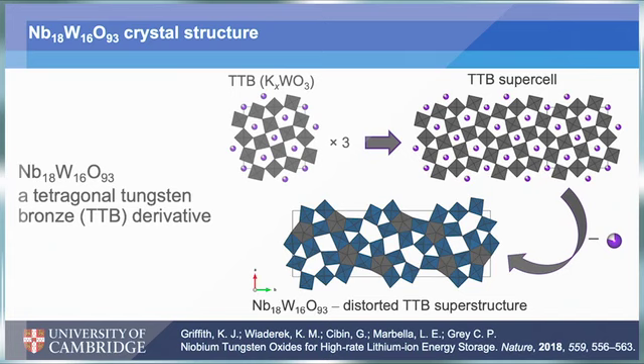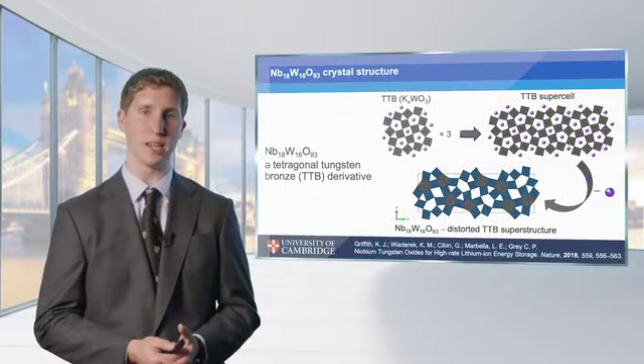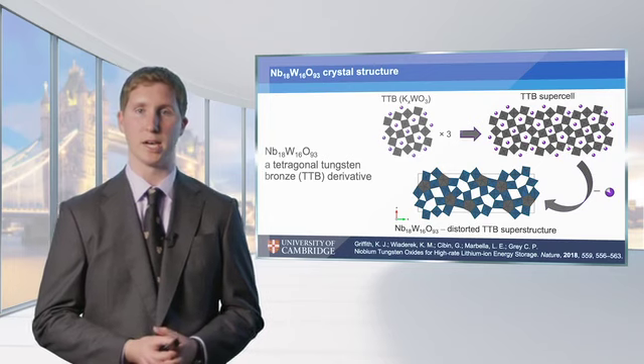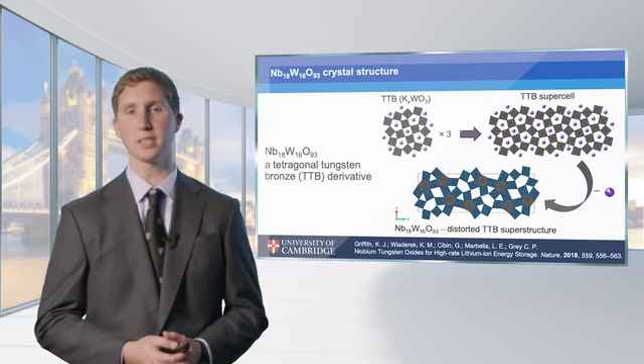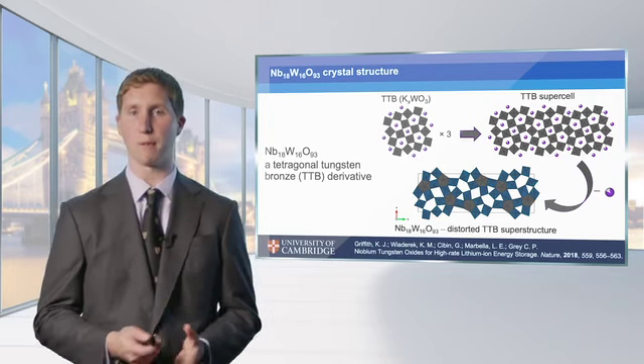The difference here is that rather than having a stabilizing and reducing presence of something like potassium, we actually place some of our niobium and tungsten atoms into those tunnels and form these pentagonal bipyramidal tunnels that stabilize the structure inherently. And so that means we start with a fully oxidized network, and we can get the maximum amount of capacity out of our structure from the time that we start lithiating.